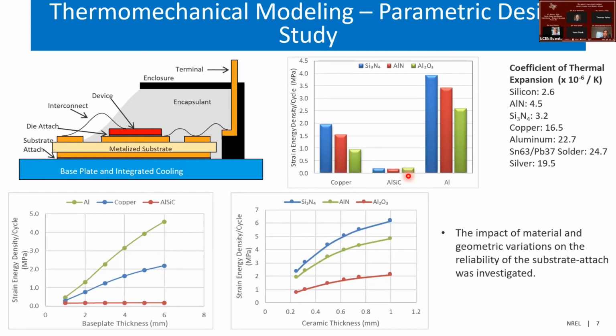That's how this is helping guide design. This is showing the benefits of the aluminum silicon carbide base plate. It's showing how these different ceramic substrates stack up against each other in terms of performance. Also, increasing base plate thickness can increase the stiffness, and hence we are seeing higher strain energy density per cycle, and that may result in lower reliability. Same with the ceramic thickness as well. Increasing thickness means increasing strain energy density, potentially lower reliability.